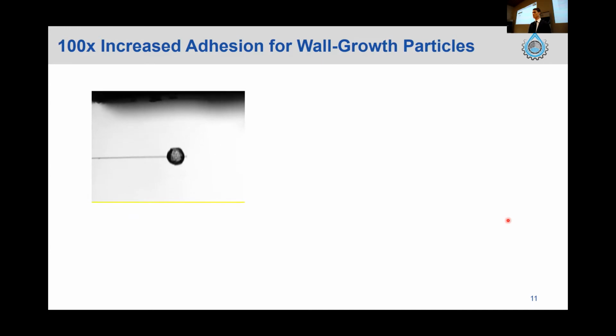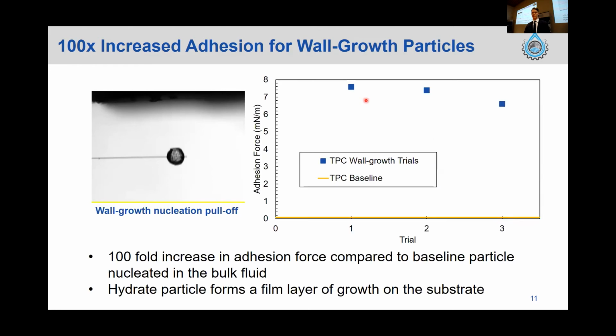So you can see visually how that was a much larger displacement than the previous two. And you could see a bit of the hydrate film coming off, which was contributing to that adhesion force, which required a much larger pull-off. And so basically here is just plotted the 3 individual trials that were done. For these ones, there weren't repeat pull-offs performed because, as you could imagine, once that hydrate particle had been pulled off, that structure was changed and couldn't be reattached basically by putting it back into contact.